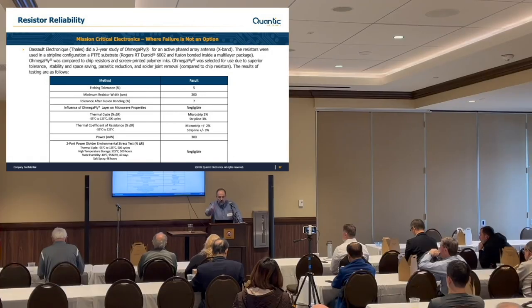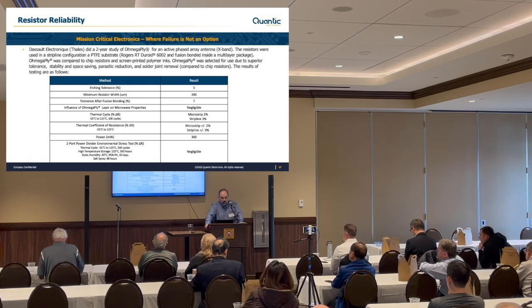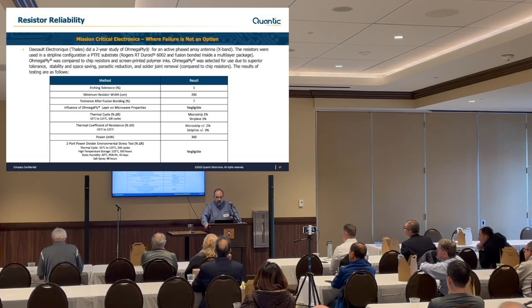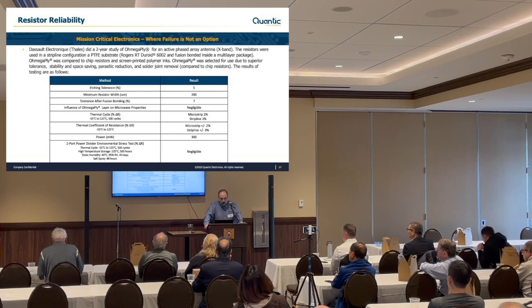And so you mentioned the temperature coefficient of resistance. For both microstrip and strip line it is less than plus or minus 2% shift over the range of -55 to 125. So again, it's pretty stable material. You don't see much of a change over the typical temperature ranges you're going to see. Again, we can put milliwatts. Everything's typically going to be milliwatts. You're not going to be driving a lot of power through these things. But then again, most circuits don't require all that much power for these type of resistors.